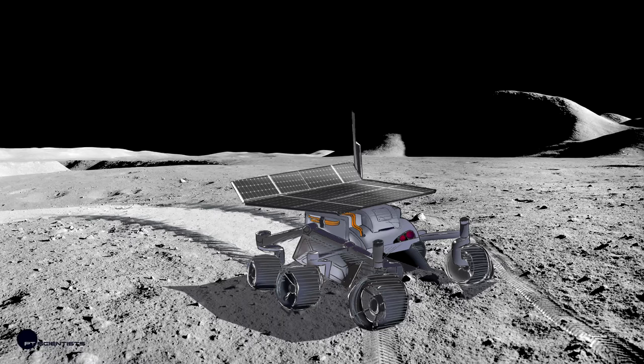One proposal is a boring lawnmower concept, but we think something cooler is better. The idea is that you have magnetrons on the bottom side of a vehicle, and while you're driving you irradiate the surface. This irradiation brings the material to about 1,200 degrees Celsius very quickly, starting a melting process that gives you a very nice coating. Because we're using microwave, this is a very power-efficient way of doing that. This is why we're aiming to send a small experiment to the surface of the moon using the microwaving approach.